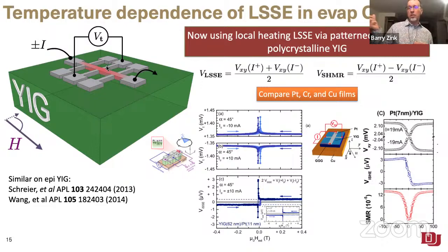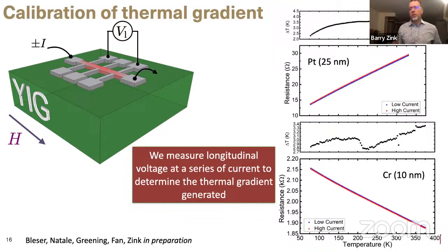Of course, if you then subtract those two, the positive current and then the negative current effect, and then divide by 2, you're looking at things that should be electrically generated, or that could be predominantly electrically generated. And so the typical thing is to call that the spin-Hall magnetoresistance. I think to really firmly show that it is actually that physics, you have to be a little more careful. But in any case, those are the electrical effects that you can probe in the same experiments. All right, so this is what we're going to do to try to understand our chromium, because it's very easy to then change the temperature of that system, because it's compatible with all of our cryostats, and away we go.